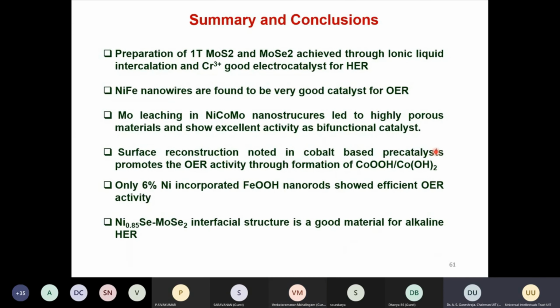So in summary, what I will try to convince is that the preparation of 1T MoS2 and MoSe2 is achieved through ionic liquid as well as a chromium-doped sample, and both samples show better electrocatalytic activity for hydrogen evolution, and nickel nanowires are found to be a very good catalyst for oxygen evolution. Then I have shown examples of this tri-component system of nickel, cobalt, molybdate, where we found higher activity due to the leaching of the molybdate, which was extended to vanadate as well as phosphate samples.